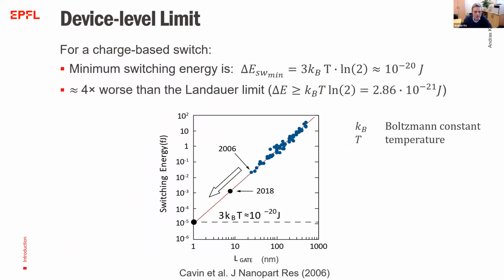So now if we want to figure out what are the performance and the theoretical limits for the power dissipation that we could have in a single transistor-like device and how far we can actually go by scaling, we need to look at the Landauer limit, which for a transistor-like device, for a charge-based switch, basically tells you that the minimum energy that you need to dissipate simply from a thermodynamic point of view is 4 times the Landauer limit, which is the basic limit that comes from the fact that if you switch a transistor and you don't keep track of its state, then you're erasing information and you're increasing the entropy of the universe.